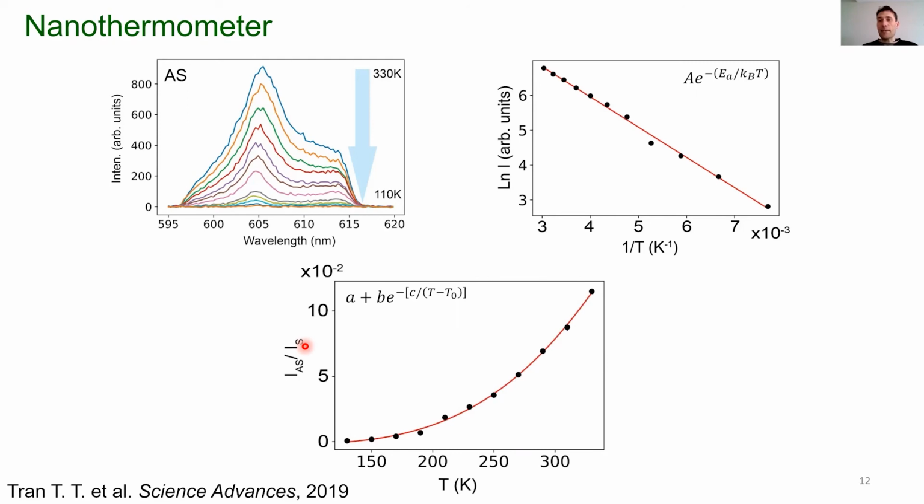Because let's say that we have this nanodiamond inside a cell that is absorbing really, really hard at a certain wavelength. Well, this absorption at that wavelength will occur both when we excite with the Stokes and when we excite with the anti-Stokes. And so by taking the ratio between the two, we can simply get rid of this absorption or scattering effect. We have, if you like, an absolute measurement. And again, in this graph, as you can see, it follows really nicely an exponential behavior, and the error bars again are the same size as the data point.